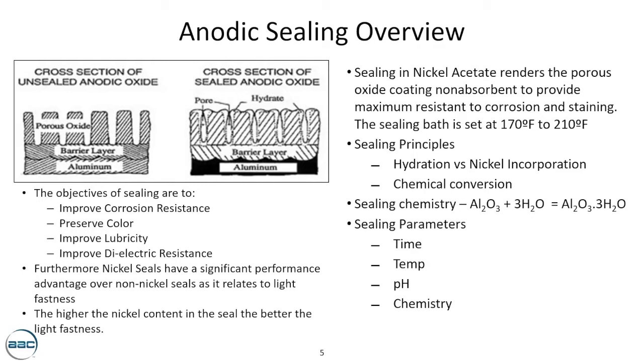Now, during that hydration process, you're taking aluminum oxide and water, and you are essentially hydrating the coating by creating a hydrous phenomenon, which is the Al2O3 with the 3H2O. And by doing so, you're pinching those pores shut. So it's a curing of the anodic coating in a way.